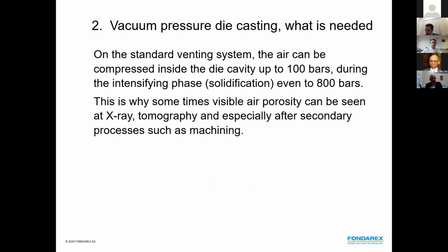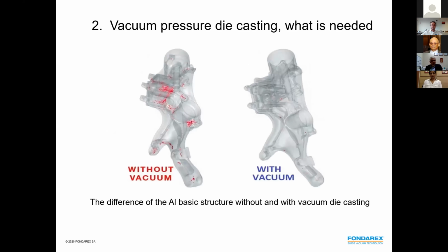Going a little further, I will later show you some curves on that. In the solidification phase, it is 100 bars, and in extremes it can go up to 800 bars. So there will be a very, very small air bubble, which is compressed during the intensification phase up to 800 bars. And then, of course, during solidification, once the pressure is no longer applied, this pressure goes back, and therefore we show a visible porosity. So this is how it looks in a tomograph.